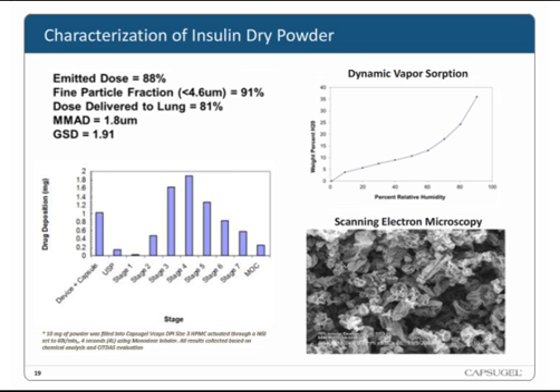And as I said, this has all been published, and it's all in the paper. If anybody would like more detail, they can find it there. And so what we found was, as we expected, a high emitted dose. The fine particle fraction less than 4.6 microns was very high.